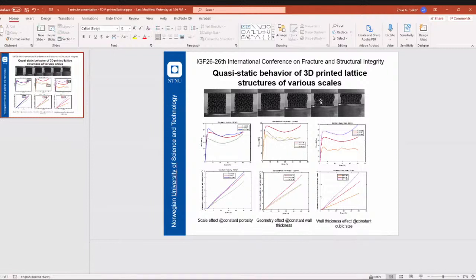Use plus minus 35? Yes, we haven't, because in this case all the printing process parameters are fixed. So yes, plus minus 45, as we found in the literature, is the most resistant to mechanical behaviors so far for PLA filament. So in this case, we only tested plus minus 45. We haven't tested other raster angles yet.